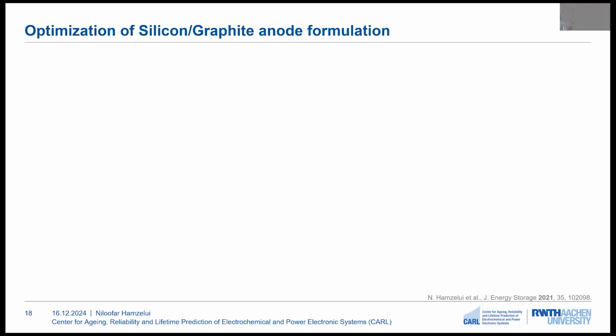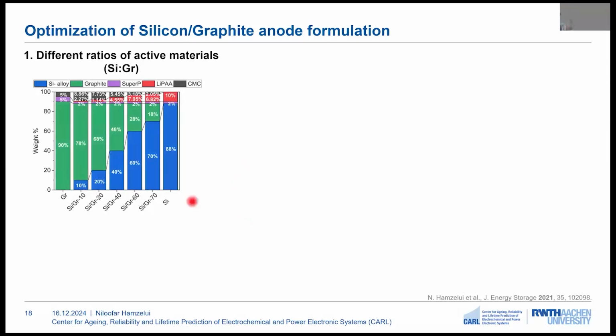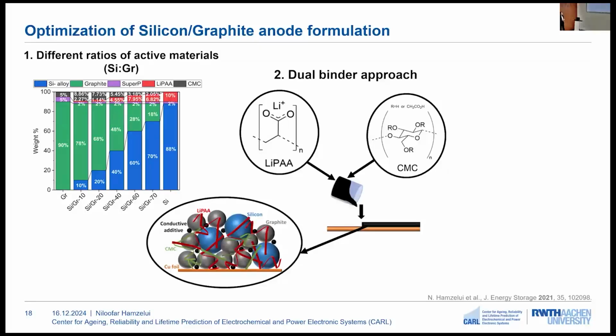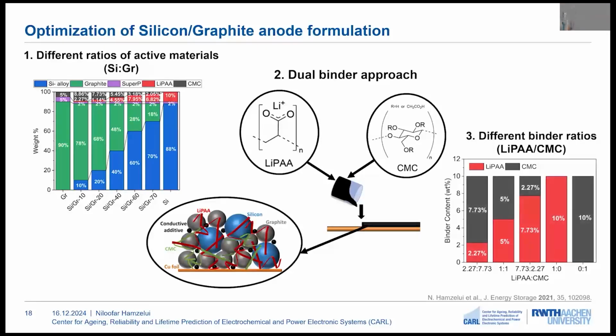So first of all, the formulation of the silicon graphite electrode was optimized. As can be seen here, different ratios of silicon to graphite were used, from pure graphite to pure silicon. It should be noted that the silicon used in this work is a silicon alloy, but for simplicity during this presentation, it will be referred to as silicon. A dual binder system was used with this electrode, using lithium polyacrylic acid and carboxymethyl cellulose. And finally, different ratios of binders were also investigated to further optimize the electrode formulation.